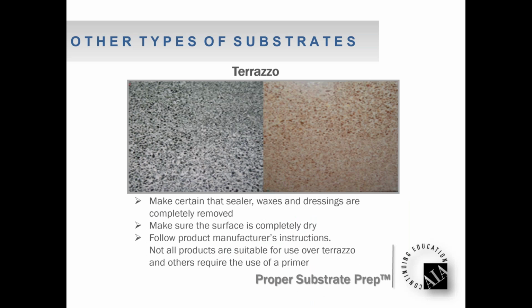Terrazzo, okay, could be epoxy terrazzo, could be cementitious terrazzo. In either case, the material is polished and the surface ends up being virtually non-absorptive. In addition to it being polished and non-absorptive, in a lot of cases, there could be a sealer, could be a dressing, could be a floor finish. We got to get down to clean terrazzo, okay? If it's epoxy terrazzo and we strip any waxes or dressings off, mechanically remove those, get down to clean terrazzo. In most cases, you got to use the appropriate primer to get a chemical bond to that epoxy.